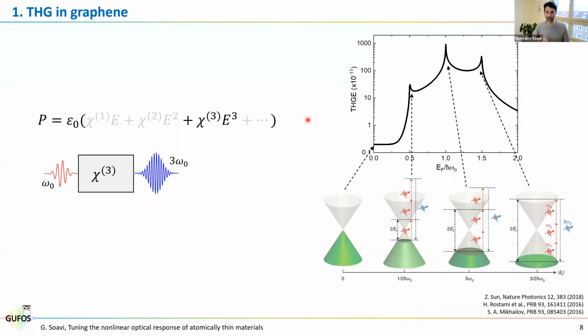And now if you look at the theory, what the theory will tell you about the third harmonic generation efficiency, the graph here, as a function of the ratio between the Fermi energy and h bar omega 0. So the doping and the incoming photon energy. This is exactly what you read on this graph. So when you're close to 0 Fermi energy, this cone here, then the efficiency is very low. And then you will see 3 very sharp peaks. And these sharp peaks correspond to these 3 conditions of multi-photon resonances. Okay, so this is what the theory tells us.